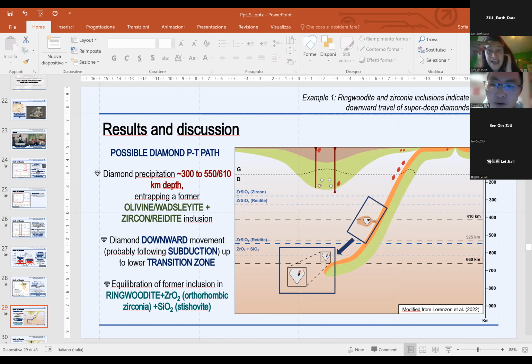And you say it is homogeneous, but for us it's not a problem, because we say that probably this diamond formed at a certain depth and subsequently traveled downward, but during this travel this diamond probably did not precipitate another layer of diamond. Okay, it reached the transition zone, but at the conditions of the transition zone, this diamond stayed in the transition zone, and the new inclusions equilibrated, and subsequently this diamond returned to the Earth's surface in the kimberlitic magma.